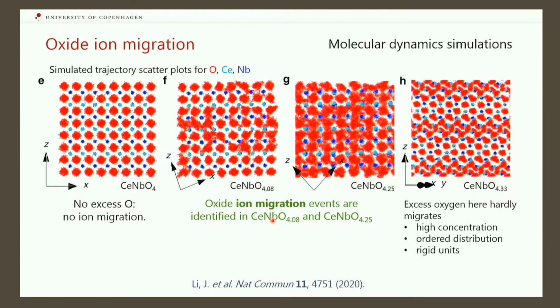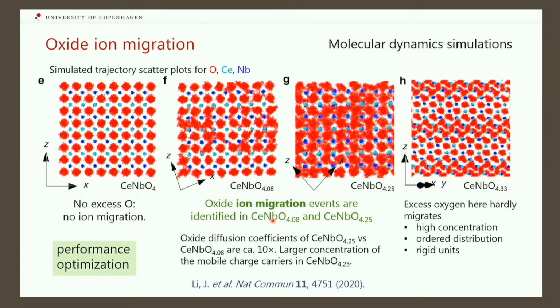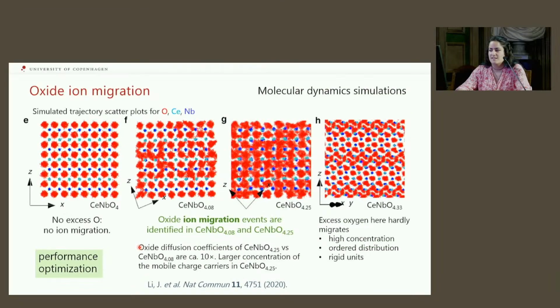So from these simulations, we can calculate the diffusion coefficient and then see that this phase, for example, is a much better conductor than this phase. So we can see that from the detailed structure, we can calculate properties and then in the applied case, optimize the performances.